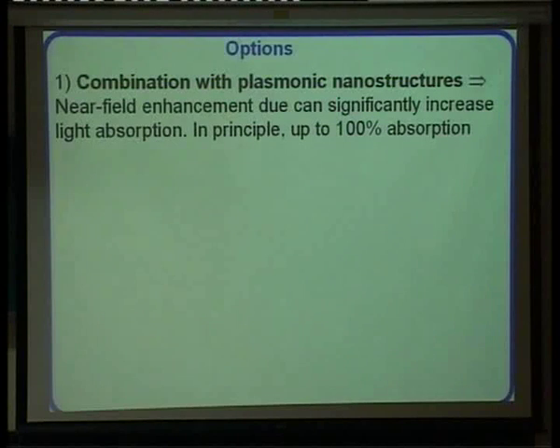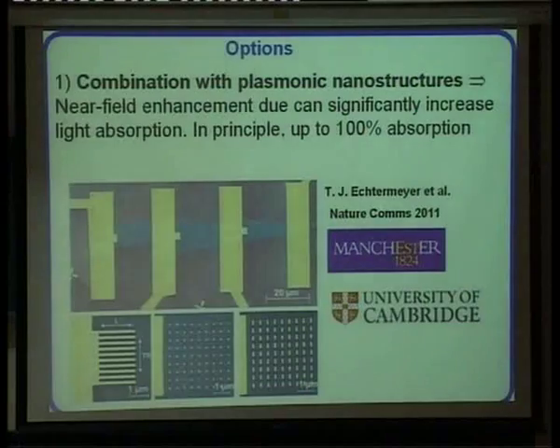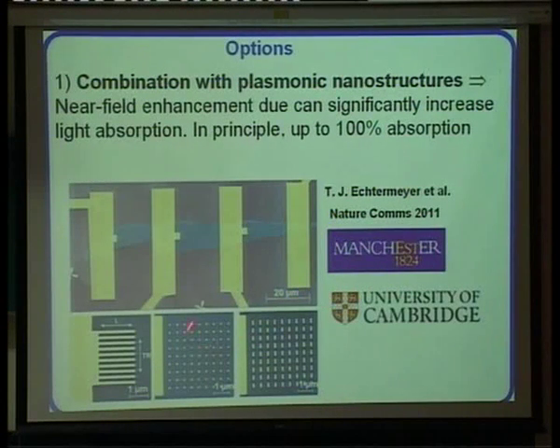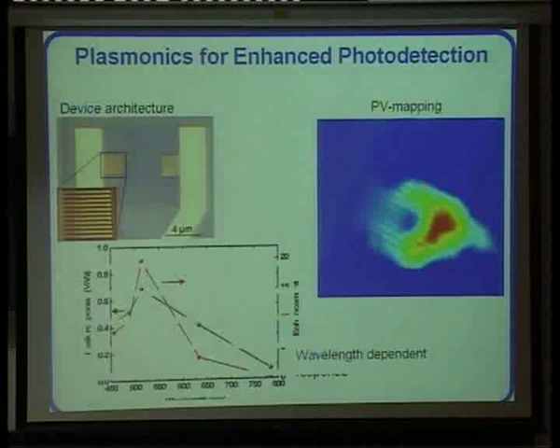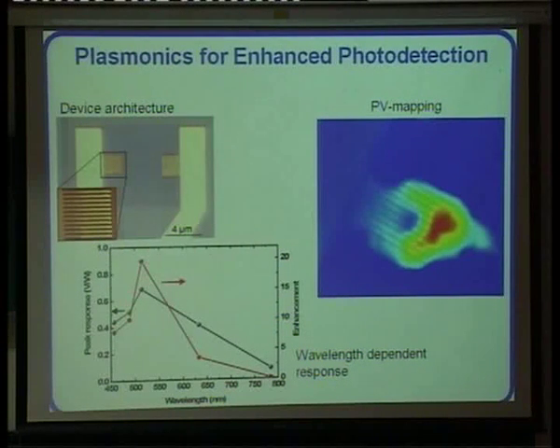So there have been different options. One is the combination of graphene with plasmonic nanostructures, such as metallic nanostructures. If you have a metallic nanostructure, the local electric field is increased. Since graphene absorbs 2.3%, if the electric field is hugely increased, the absorption of light is hugely increased. And in 2011, we showed with Manchester this combination of gold quantum dots with graphene, and the initial results showed an increase of 20 times in the responsivity of the material.